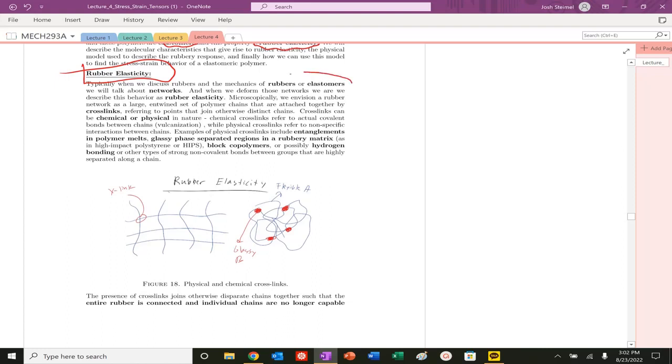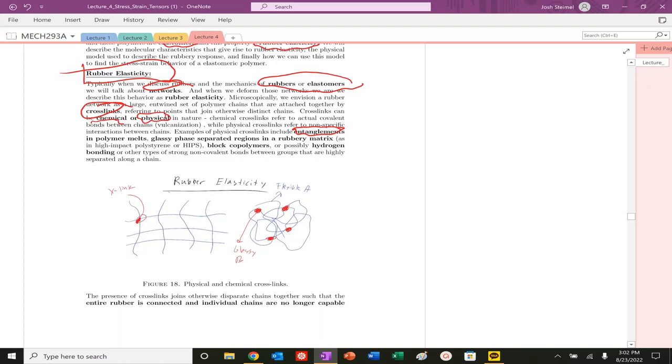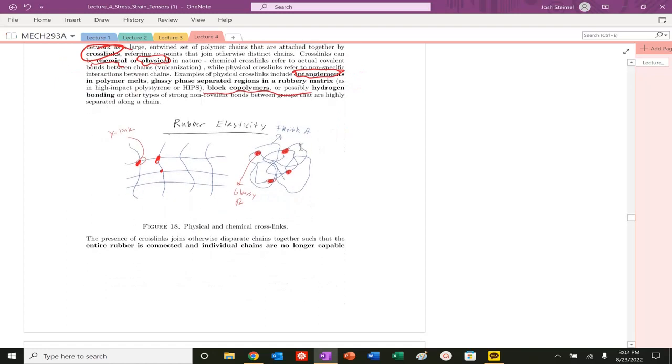When we talk about rubbers, we're really talking about elastomers, and we're talking about networks, and specifically crosslinks. Crosslinks can be chemical—most often they are. They can be physical, as long as our molecular weight is large enough. Physical crosslinks are like entanglements. Basically, these crosslinks are points—they can be either chemical or physical, or bonded as well. But these crosslinks are basically fixed at these points, so the chains can't slide past one another at this point. They're very flexible and can wiggle around in between the crosslinks, but at those crosslink positions, they can't slip past one another.